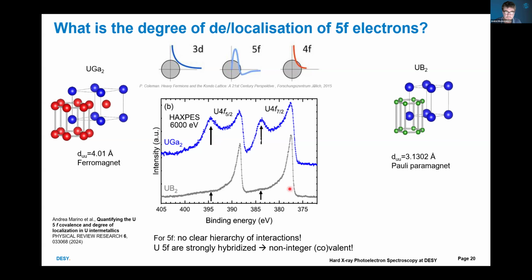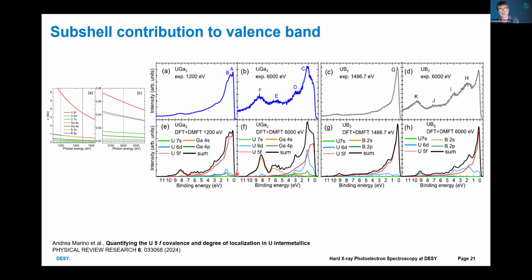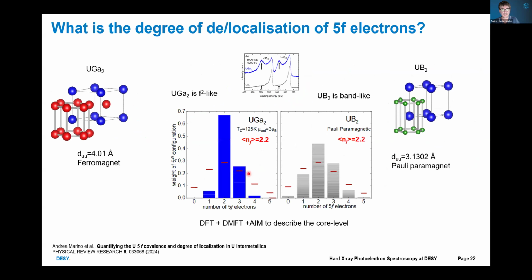They are kind of itinerant states. And in case of the uranium gallium sample, we see very clear multiplet splitting, which is the hint for strong coupling between the electrons. And of course, the theory is a bit more complicated on this matter, and we have got a theoretician who simulated all possible numbers of F electrons, and he elaborated a statistical model.